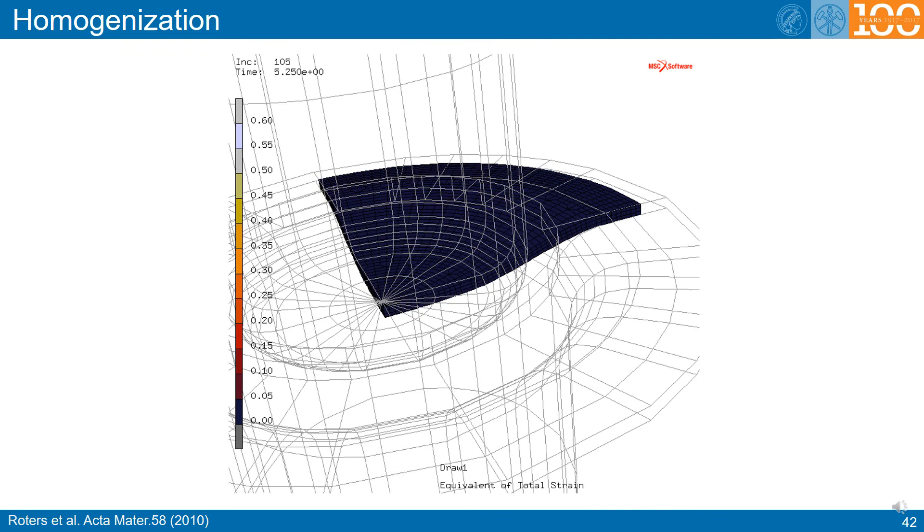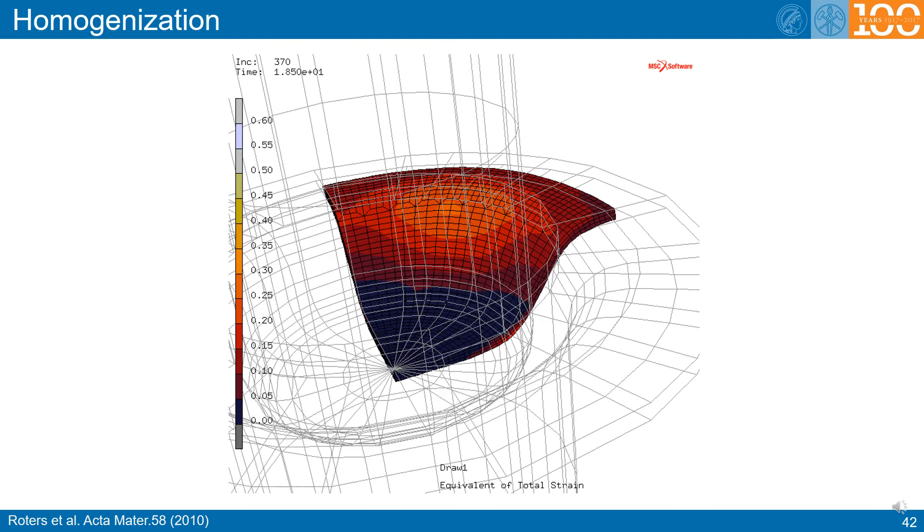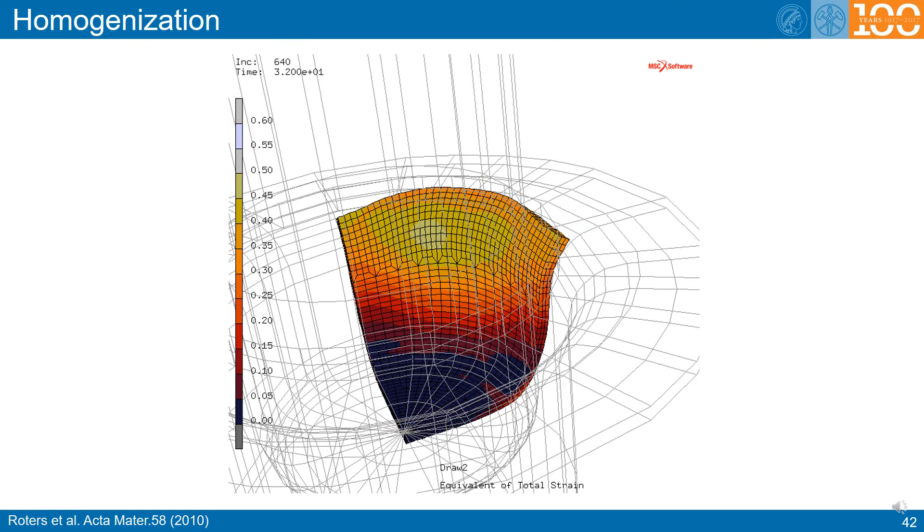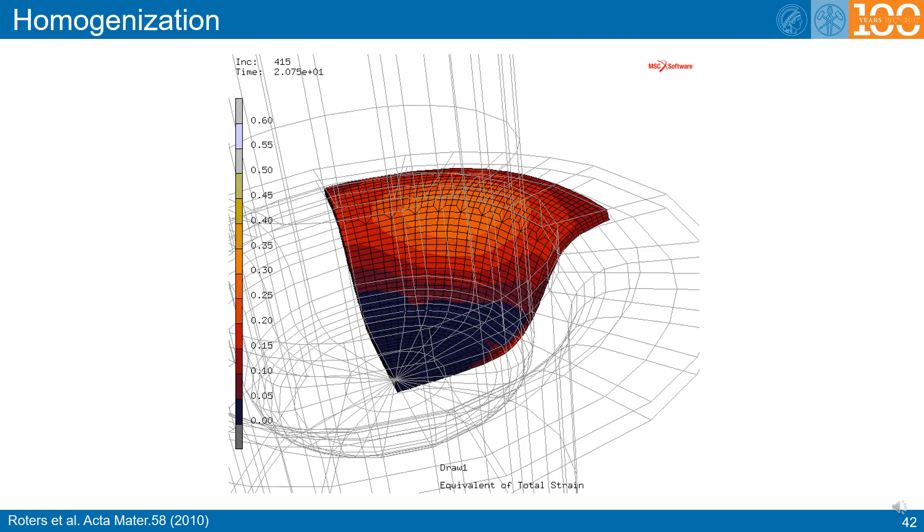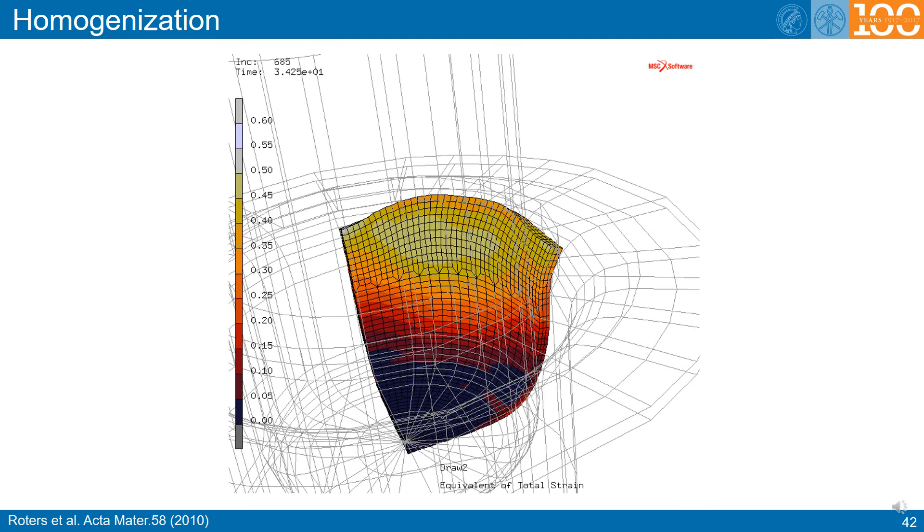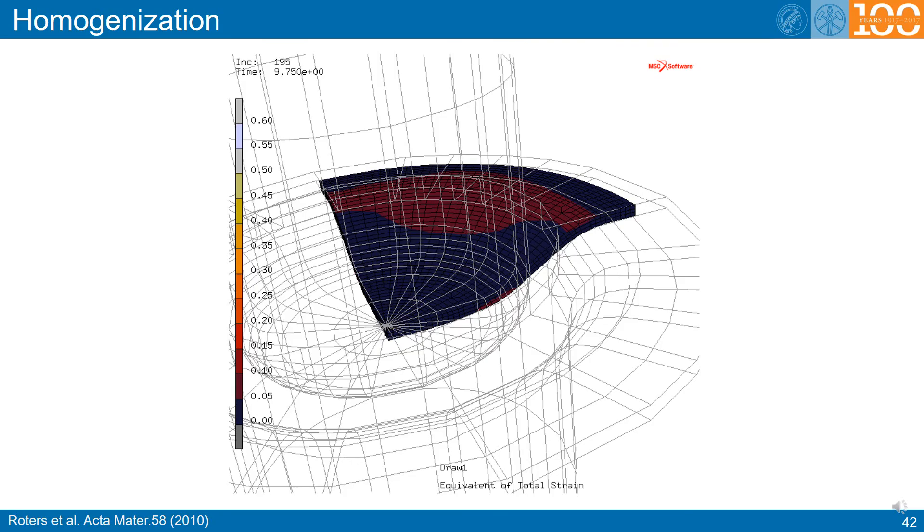Now I jump from the microscopic to the macroscopic direction. You can also use such information to subject it to a local RVE calculation, where RVE stands for representative volume element, which you then use as an integral response to feed it, for instance, as a constitutive law here into commercial finite element calculations from Marc. Or you can do the same with Abaqus. But as you see here from the appearing earing, from the deep drawing operation, this is fully informed by the underlying physics.